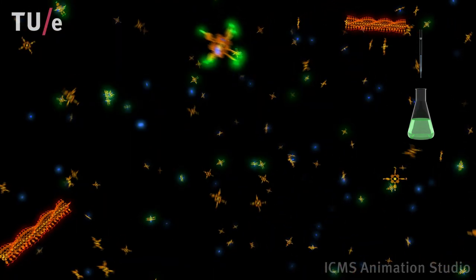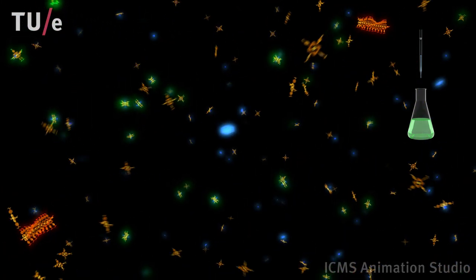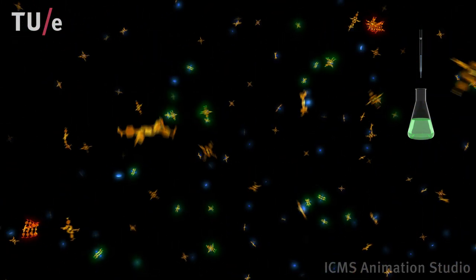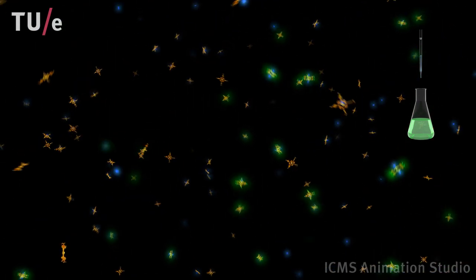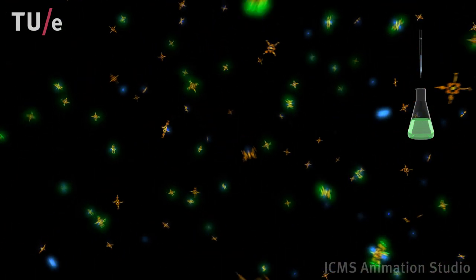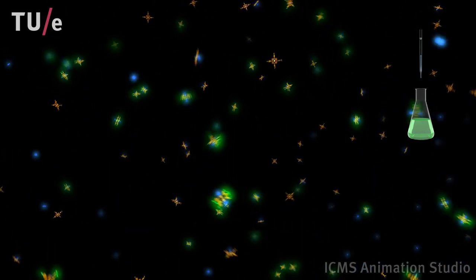This system can be described by coupled equilibria in which cooperative hydrogen bonding competes with metal-ligand complexation. Thus, at a fixed porphyrin-to-pyridine ratio, the porphyrin stack length is determined by the concentration of the entire system.